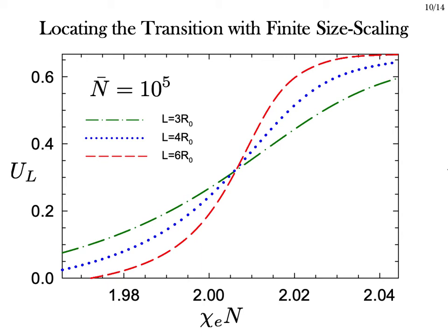This is because it has 3 fixed points. At high chi-n it tends towards 2/3. At low chi-n it tends towards 0. In between there's a third fixed point at the critical point. These fixed points don't depend on system size. This isn't too useful for the high and low fixed points, however the one at the critical point becomes quite useful. This is because it allows us to conduct simulations at different system sizes, calculating a curve for each system size, and look for where the curves overlap. This gives us a very precise location of the critical point.